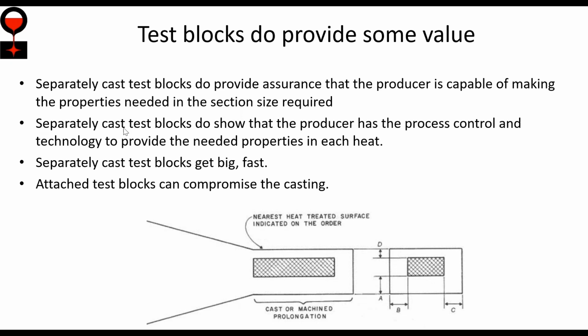If you have me do a cast test block with every heat, that shows that not only can I do it one time, but that I can do it every time, so that I have the process disciplines, the skill, and the capability to make those properties in each heat. So if you have a critical casting, a separately cast test block can be a useful guarantee that you're getting the properties with every heat. And if that part fails, it gives you documentation that the part was made correctly and had the properties you anticipated. But you have to recognize that separately cast test blocks get big fast.